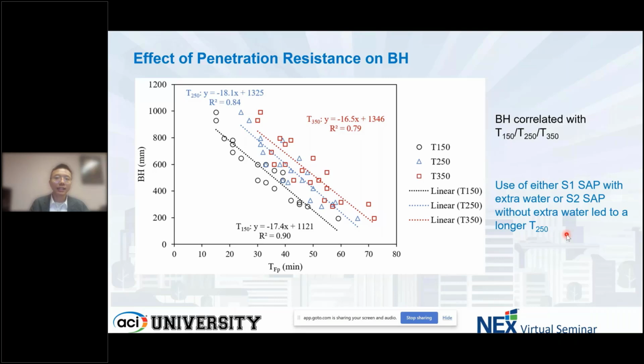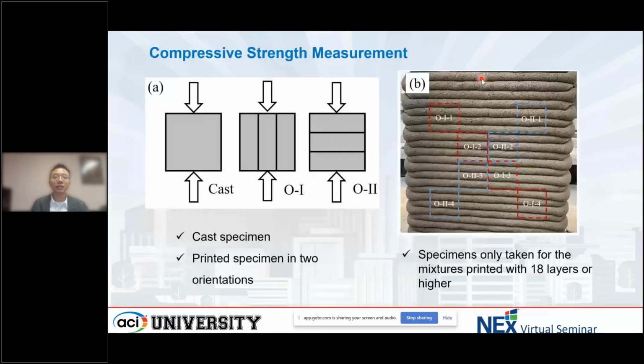So as it reduces the buildable height, another question is why we use SAP? Because printability is also another important factor, and that's why, as I mentioned, the answer is it improves the printability, and printability is also very important, as I described earlier. It improves the surface quality of the filaments, and it also improves the interlayer bond between layers, and then it results in better strength.